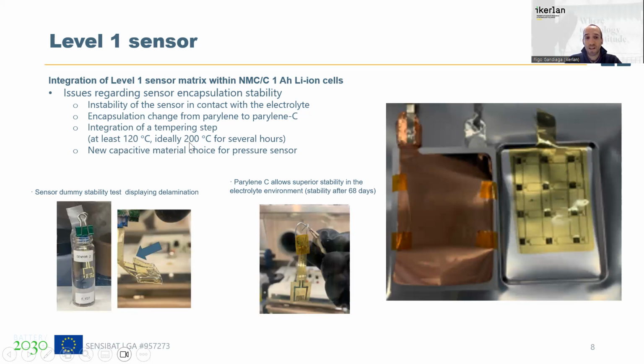This high temperature process did not affect the temperature resistors, but it affected the capacitive material of the pressure sensors. So we needed to start again from the beginning and change these capacitive elements, because the ones that were selected at the beginning cannot stay at these high temperatures.